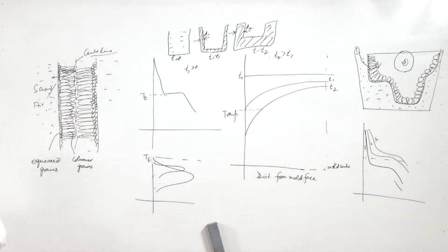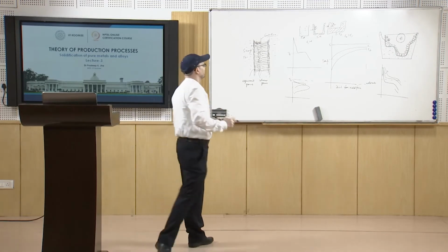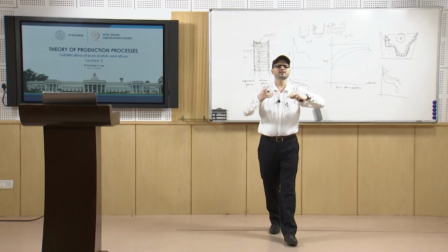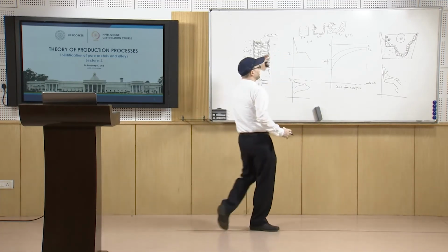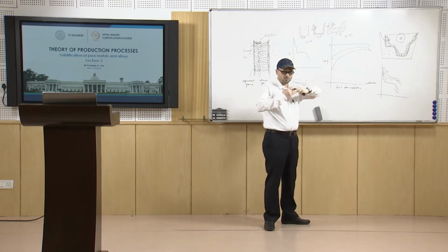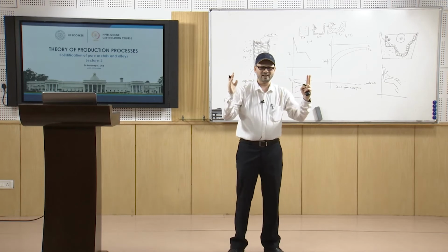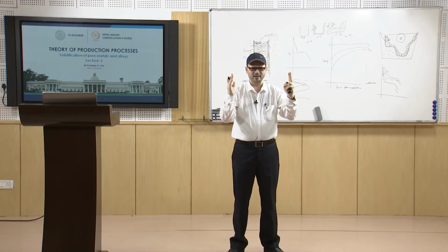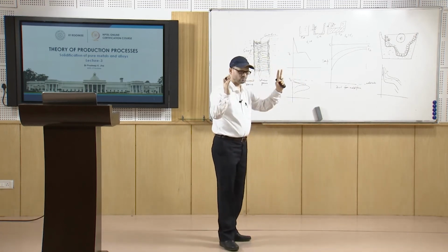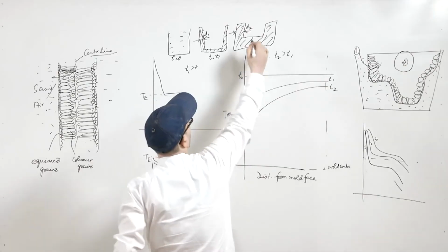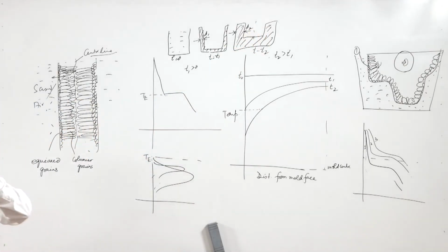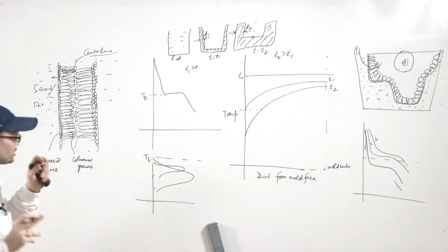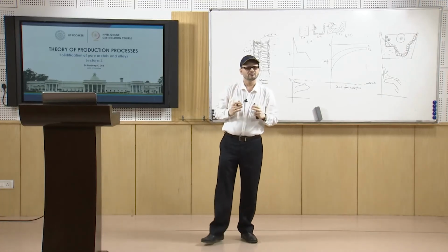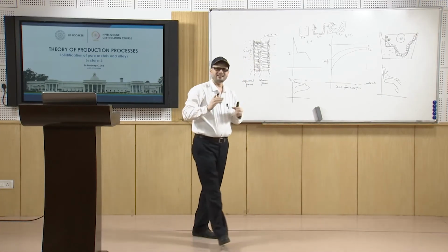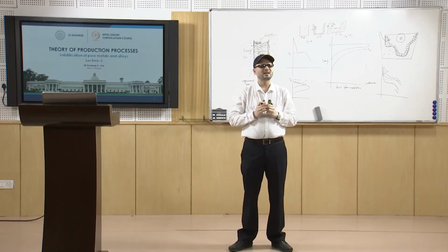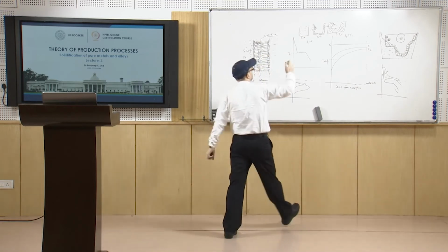So this way as the time progresses, the thickness of the solidified shell goes on increasing, and it is increasing in a planar way. So the front is moving in a planar way from both the sides, in a straight line way, as you see here, that they are moving on the inner sides, and it will go till it reaches the central portion. So at certain time it will completely solidify. So this is an example of plane front solidification. So what we see is that this is a case of plane front solidification, and the solidified layer is known as the skin.